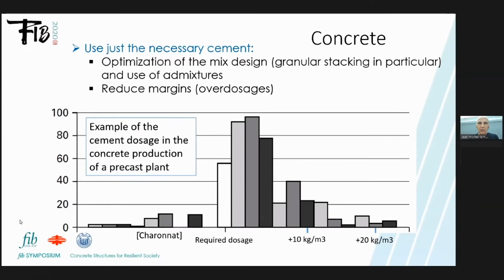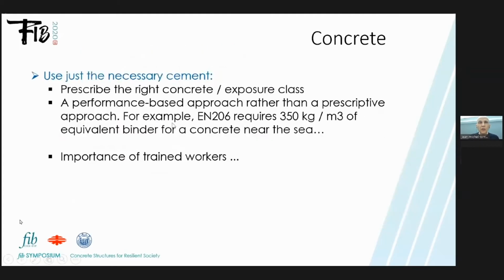So it's a way, of course, in the precast plant to be on the safe side, but if you are on the safe side, you are in overdosage, in fact. Of course, we want to use just the necessary cement, so to prescribe the right concrete for an exposure class. And also we can improve the performance-based approach rather than a prescriptive approach. For instance, in Europe, if you are near the sea, you have a requirement of 350 kilograms of binder per cubic meter, and maybe you don't need that. And of course, you also need trained workers that are aware of the problem of CO2.